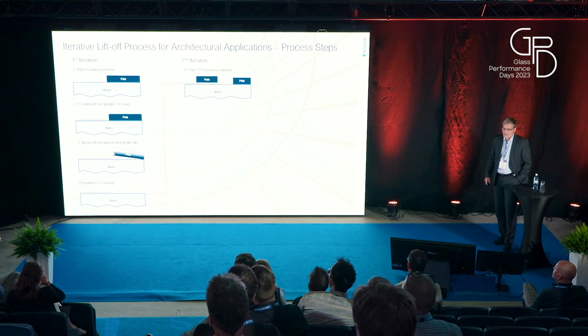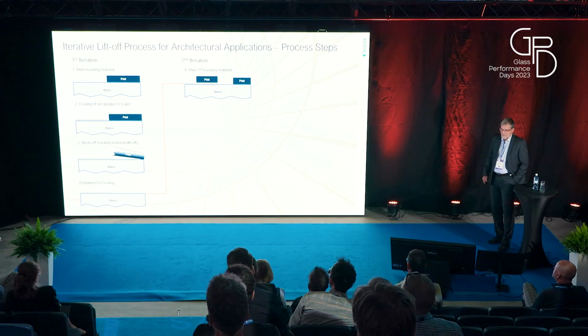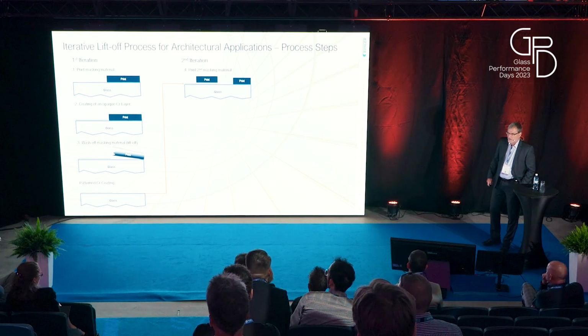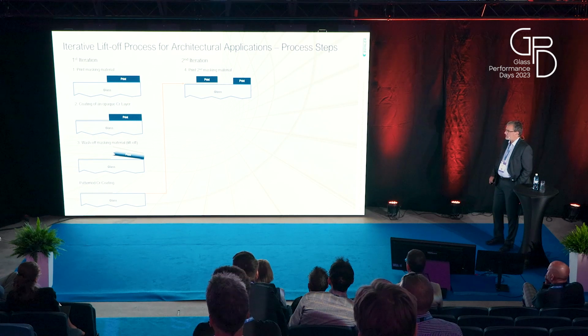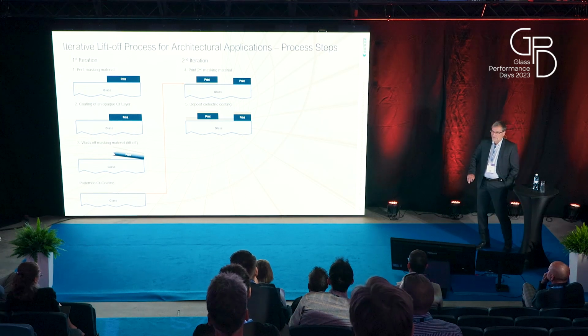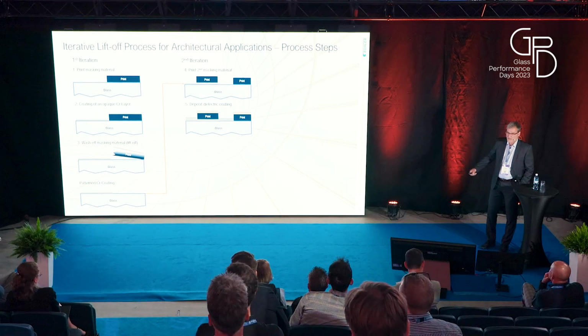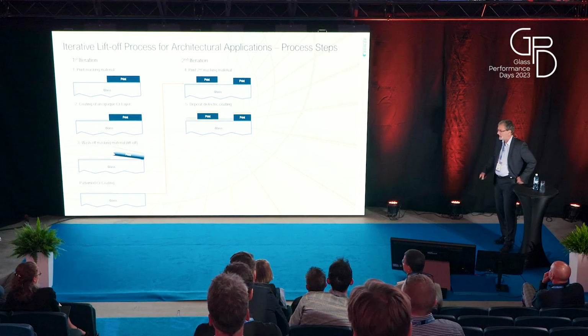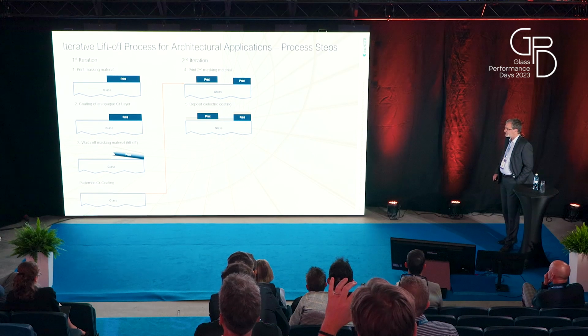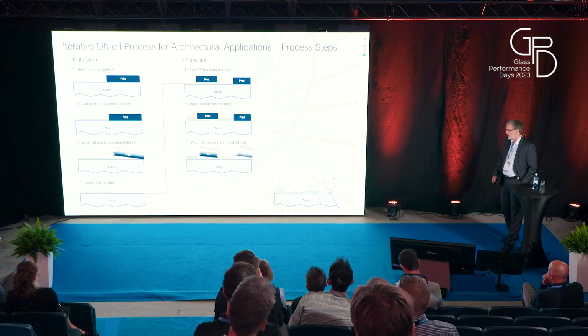And now we go back to square one and do the same, but of course we use a different mask, a different masking pattern. As you see, we also mask off the chrome layer partially, and we mask off a certain other part of the glass. Then we put a dielectric coating on top, to get a nice interference effect. This was done just for demonstration reasons, with no special spectral characteristics behind it; we did this especially for this event today. It's just a 3-layer coating, which we see in the next slide. And we again do the wash-off, mask-off, lift-off, and we get a sample like this.